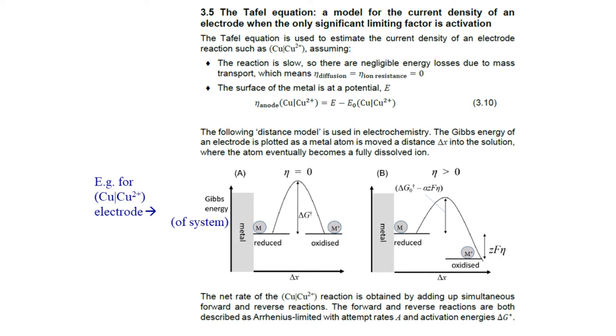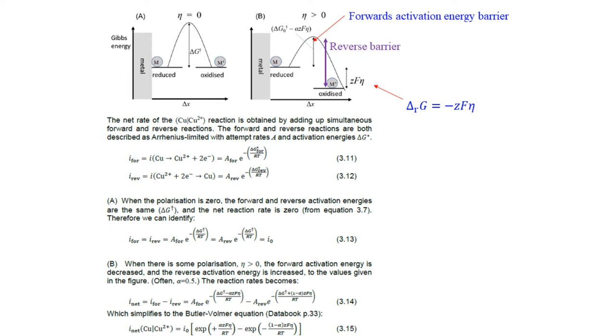Then this diagram below is called a distance model, which is used in electrochemistry to explain where the Tafel equation comes from. The Gibbs energy of the complete electrode, the entire system, is plotted along the x-axis, where we consider a metal atom being moved a distance delta x away from the bulk metal and into the solution, where eventually the atom becomes a fully dissolved metal plus ion. The net rate of this, say, copper to copper 2+ reaction is obtained by adding up, as we said, the simultaneous forward and reverse processes which actually take place.